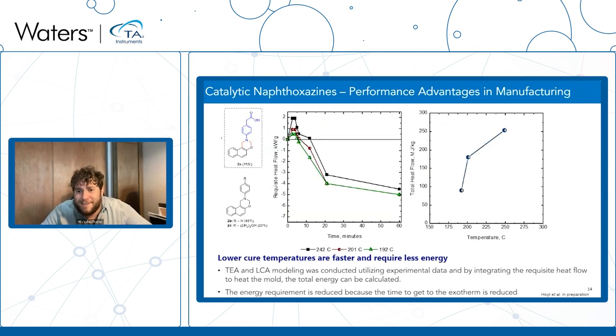NREL is an interdisciplinary lab. We get to do a lot of LCA and TEA. Our colleague, Avantika Singh, took all this. She took the heat flow that was required throughout this whole cure process. And what we've shown is that as you get reductions in the cure temperature for these naphthoxazine resins, so looking at the graphs on the right,